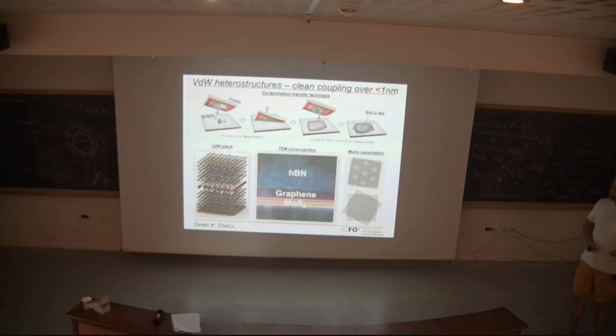Twisted bilayer graphene is made out of two separate graphene sheets, which are then transferred one on top of another. These interfaces are extremely clean, and furthermore, of course, this gives us a new tuning knob. Starting from fully two-dimensional materials and combining them gives us a tuning knob of the twist angle between these materials, which is otherwise very hard to achieve in any other fabrication method like molecular beam epitaxy or pulsed laser deposition and so on. So this is very special to 2D materials.